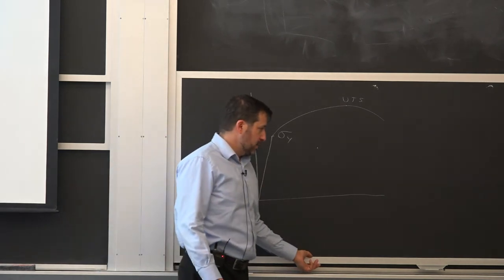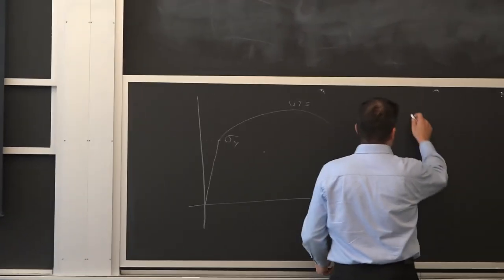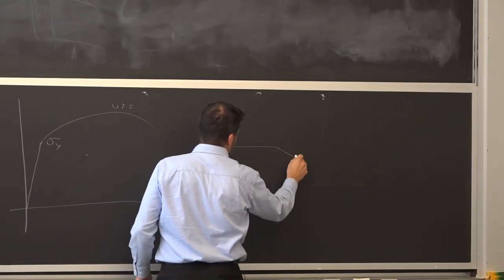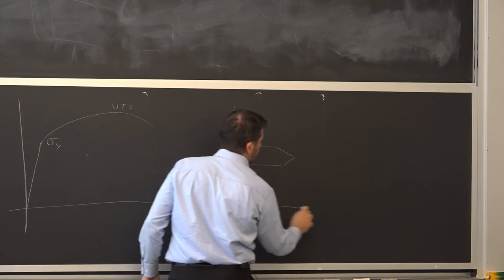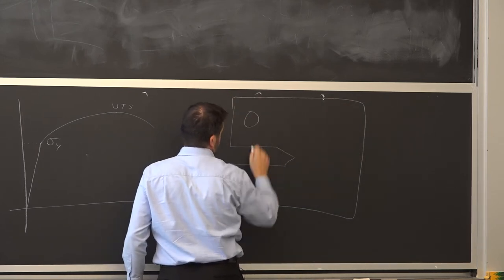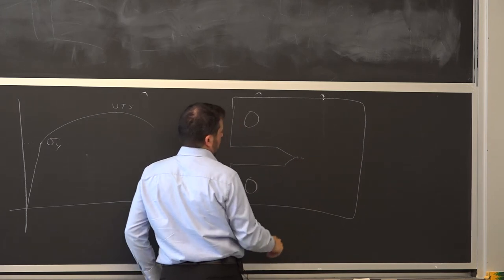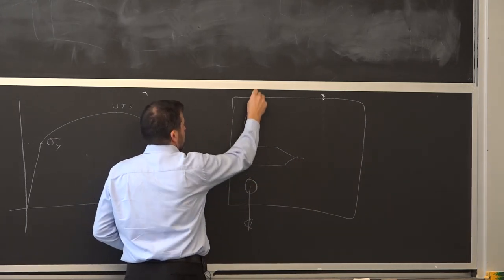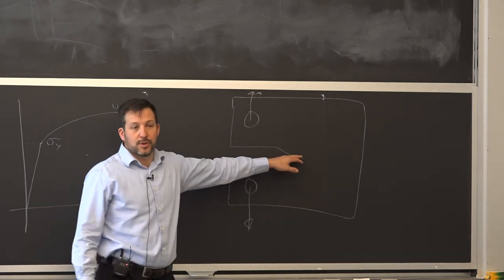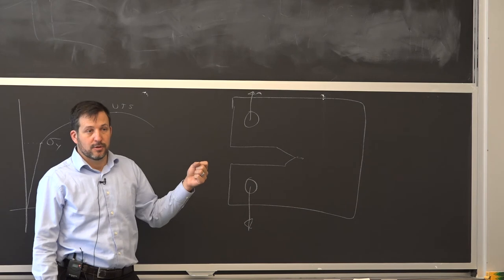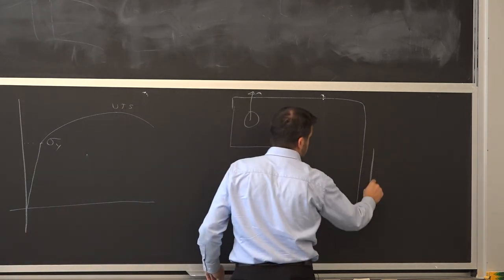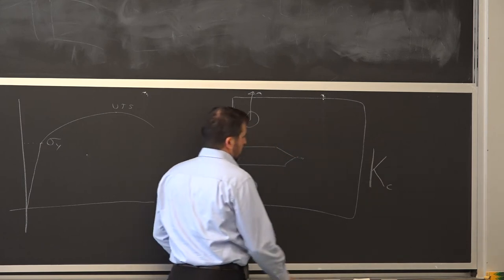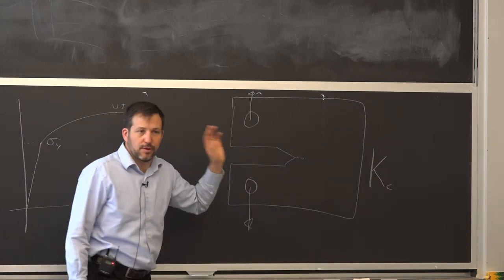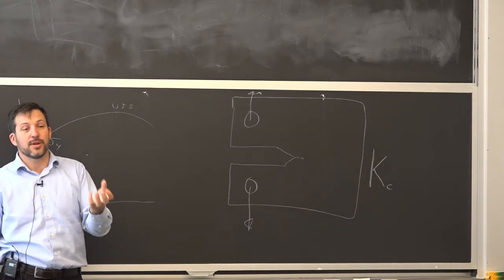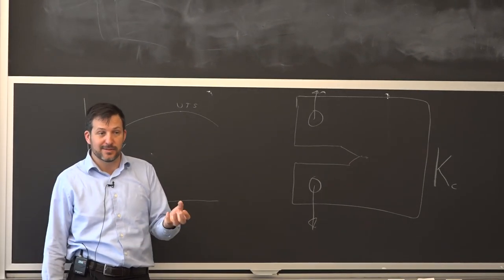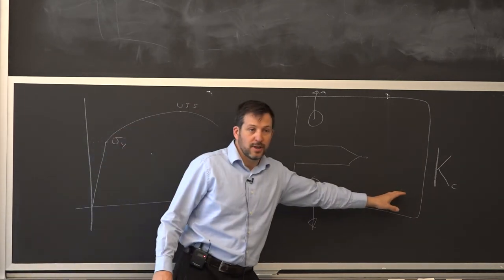The fracture toughness is a different concept that most of you are going to be very familiar with. You start with, let's say, a compact tension specimen that already has a crack in it of a certain size, so you have a little flaw. And then the question is, what is still the loading capacity for that sample with a crack to completely fracture? So here we're talking about essentially a KC for the material. There's a very simple relationship that relates your flaw size and the actual material property, the resistance for any material. If it's glass or ceramic, a very low number here, a very high number there.